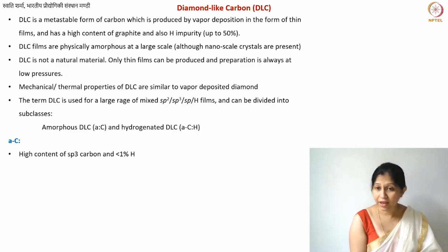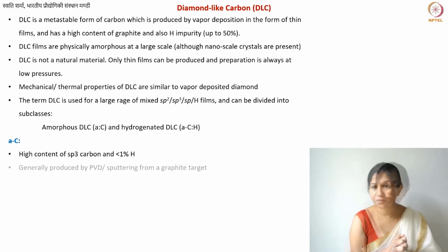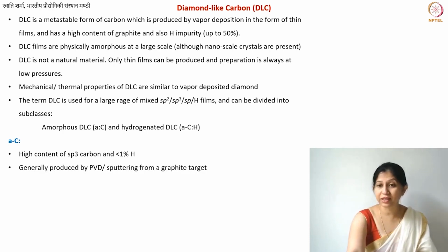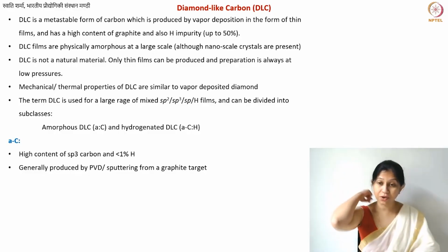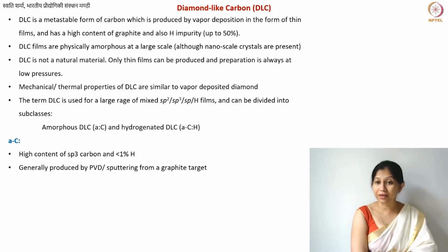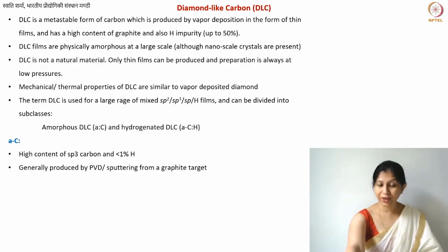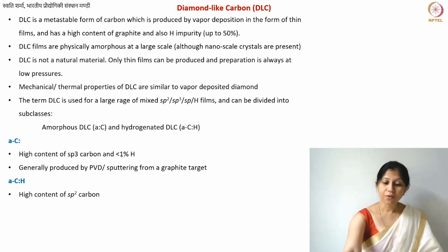Here you have a high content of sp3 carbon and less than 1% hydrogen. You will generally produce it by sputtering type methods, generally using PVD. One more thing is that you still need plasma for DLC production, but the temperatures can be slightly lower compared to what you need for vapor deposited diamond, because there the continuous presence of hydrogen species was very important, and also the continuous activation of your carbon species. Here it is also important, but since you can live with slightly lower purities, purity in terms of sp3 fraction, you can have slightly lower temperatures. So typically for this kind of carbon you will use PVD, removing carbon from a graphite source.